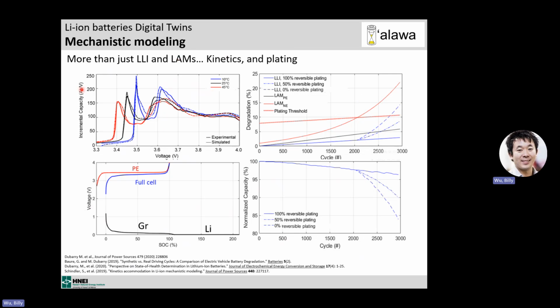Now, that curve is really interesting, and I really enjoy that one. That's to showcase the impact of kinetics. If you think about it, kinetics is just slowing your cell, if you're decreasing the kinetics, or improving it if you have faster kinetics. That's the same effect as increasing the current or decreasing the temperature. So what that means is if we test different rates, we can derate the electrode level so that we can match lower temperature by increasing the rate. And in that example here, I use data at 25 degrees in black to simulate data at 10 degrees by increasing the rate on my electrode, or data at 40 degrees by decreasing it. And you can see we can get really, really good fit.